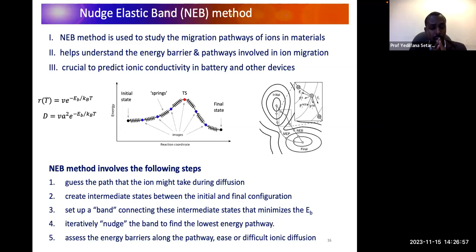So the steps to run the NEB calculation are, first, you need to optimize or relax the initial and the final state. This is the first step. And then you need to guess the path that the ion might take during the diffusion between the initial and the final state. Then you need to provide intermediate steps. Depending on the resources available, you can increase the number of intermediates, but at least you need to have one or three. We usually use five intermediates, just as you see in the middle of the slide.